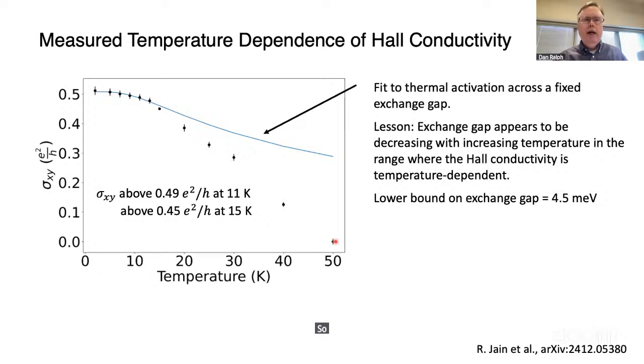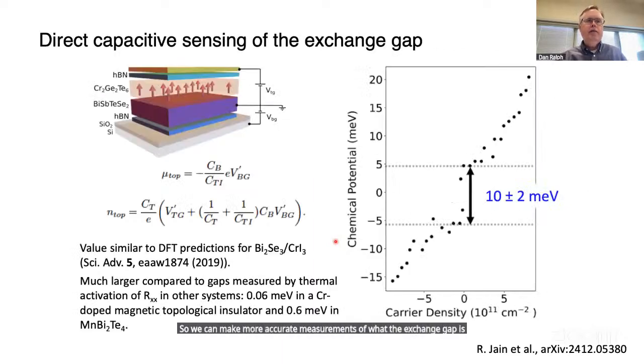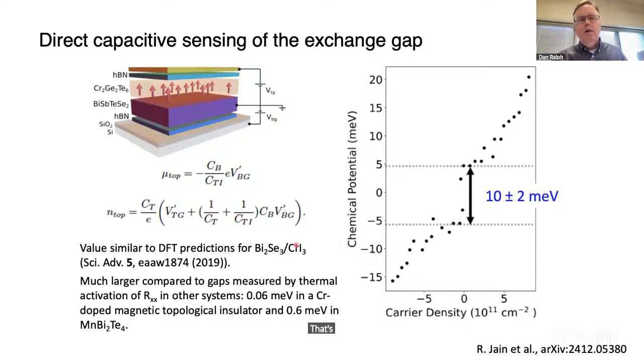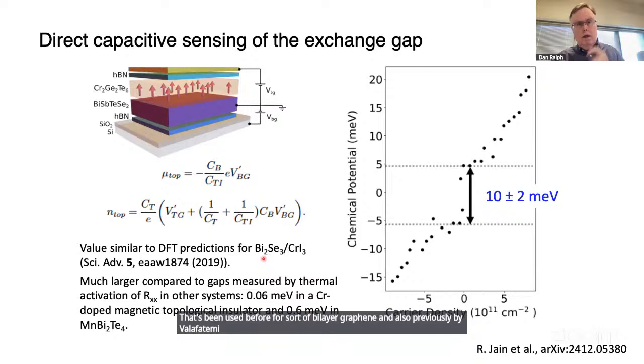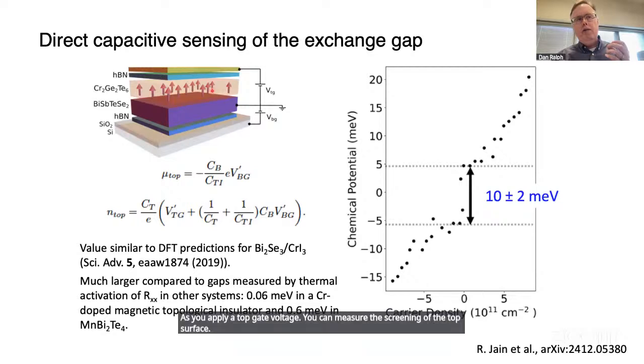So we can make more accurate measurements of what the exchange gap is using a capacitive technique that's been used before for bilayer graphene and also previously by Valla Fatemi in the Herrero group for measuring the gaps in topological insulators at high magnetic field. The idea here is to use the bottom surface, the ungapped surface of the topological insulator, as a sensor to measure the screening of a gate voltage by the top surface.